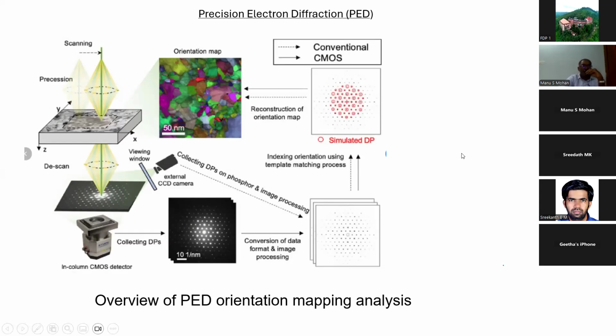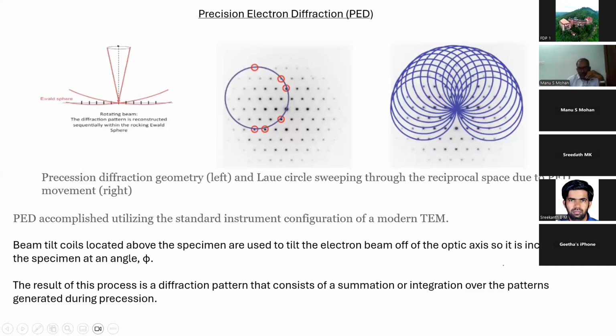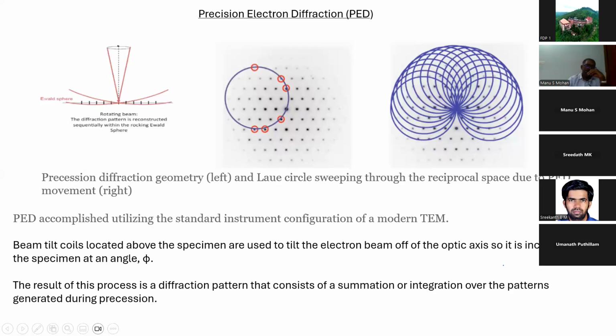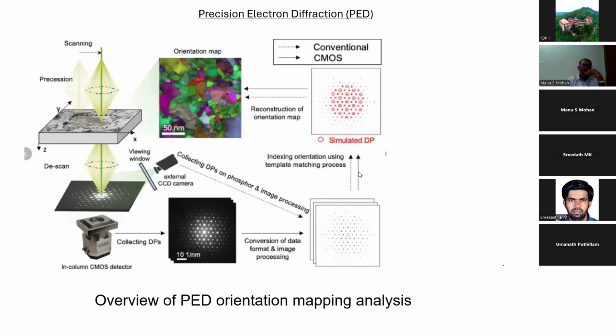So now this is what they do here. They take a crystal. Why do you have to do this? Normally, when I was speaking to your professor, Manu sir, he was telling about the EBSD facility which he utilized for his PhD. EBSD can be used to find out the orientation up to the scale of a few nanometers, like 50 nanometers or so, easily. But let's say you have features as small as 5 nanometers, which chemists or metallurgists are working with. Some of them will be a few nanometers. You cannot get the information at such a scale, even strains, magnetic domains. So you have to go with either TEM or PED.